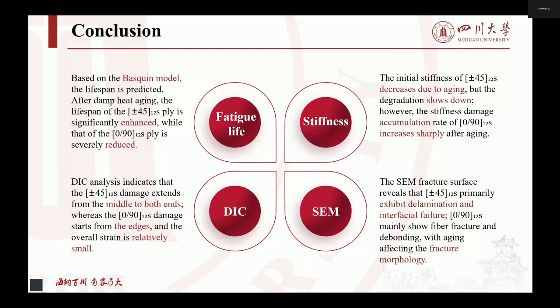The stiffness of the 45-degree laminated board decreases due to aging, but the degradation rate slows down. The SEM fracture surface reveals that 45-degree laminated boards primarily exhibit delamination and interfacial failure. 90-degree laminated boards mainly show fiber fracture and debonding, with aging affecting the fracture morphology.